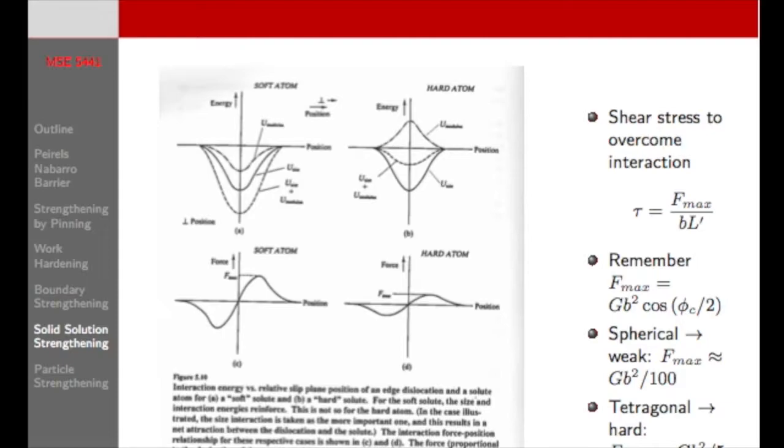But you've got to remember our Hume-Rothery. What's about the maximum amount that we can put in to get a solution across the whole range? It's about 15%. So if we have significantly more of a deviation than that, we're only going to be able to put our solute atoms in small concentrations before we phase separate.